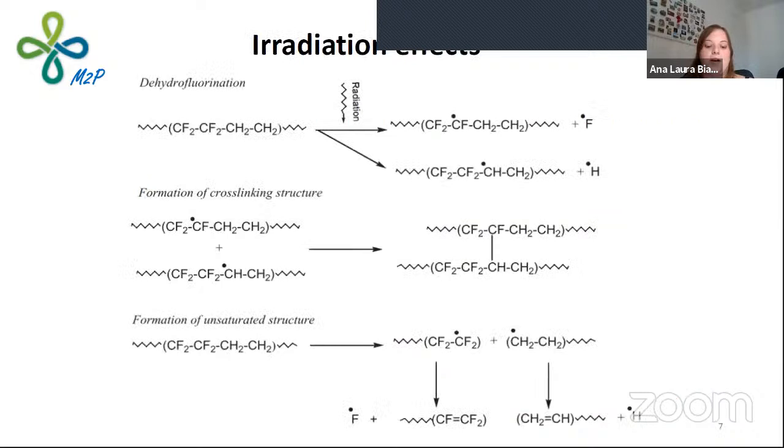So speaking of the possible degradations of the base polymer, when ETFE or any other polymer is exposed to electron beam radiation, which is our first step of the synthesis, the initial reaction involves breaking the bonds of carbon and fluorine and carbon-carbon, leading to the formation of macro radicals, as we show here. You can see the macro radicals.